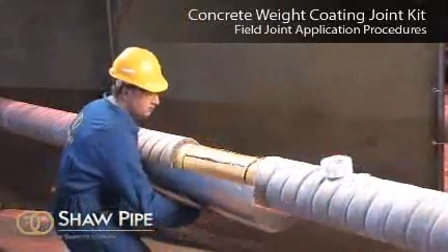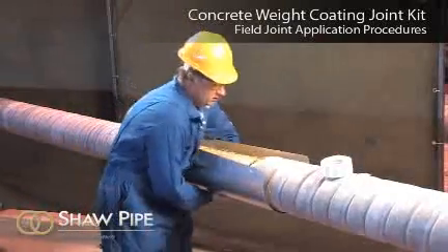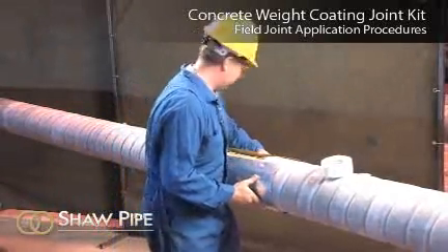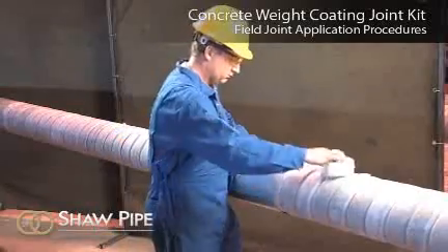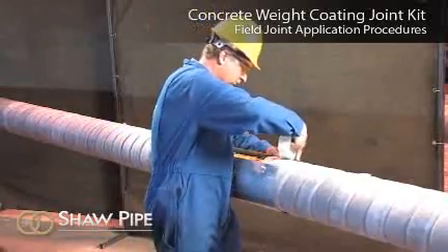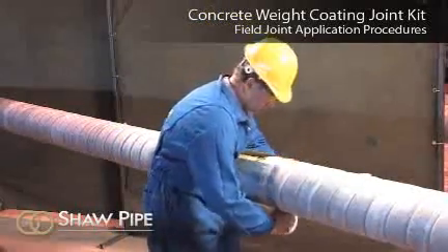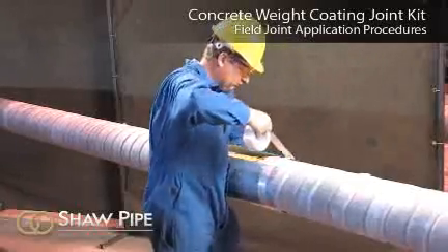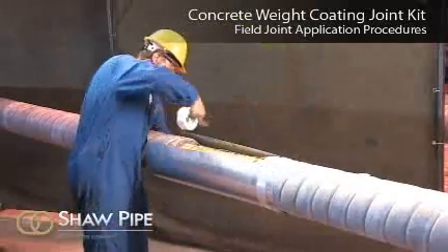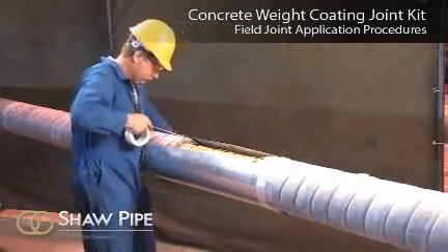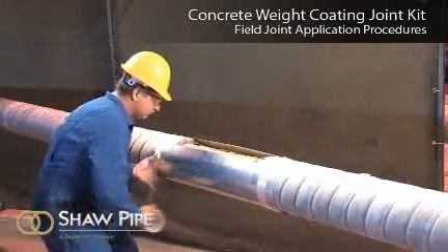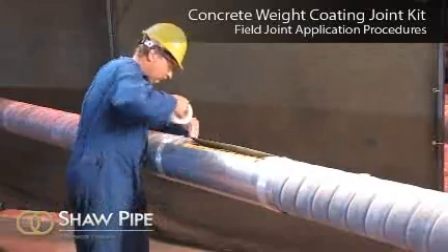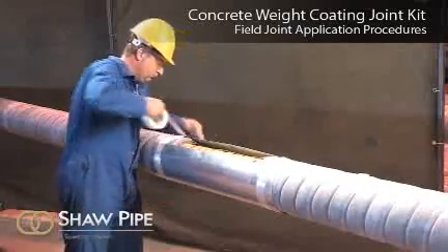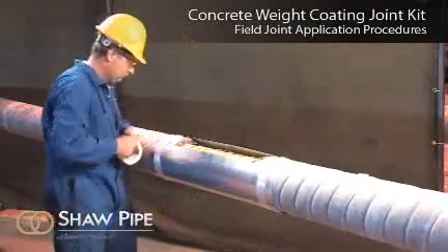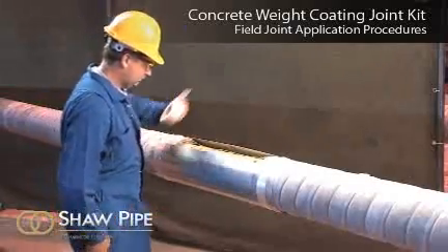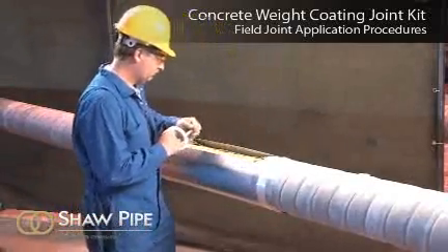Wrap the sheet metal form around the joint area so the overlap on the concrete coating is uniform on both sides. The form must be installed so that a gap, approximately 3 inches wide, is located at the top. Secure both sides of the form to the concrete coating with the supplied number 9 haywire or fiber reinforced tape. The number 9 haywire or fiber reinforced tape must be secured tightly to minimize gaps between the concrete coating and form. Any gaps may result in loss of joint material.